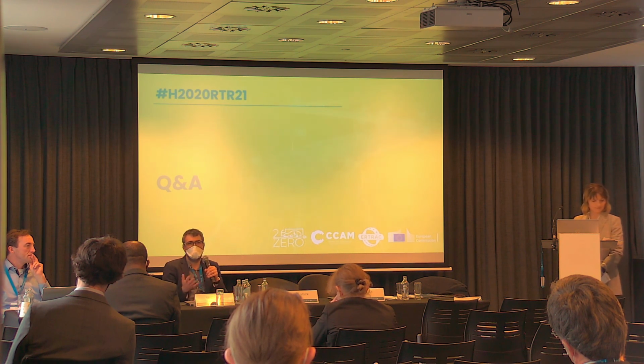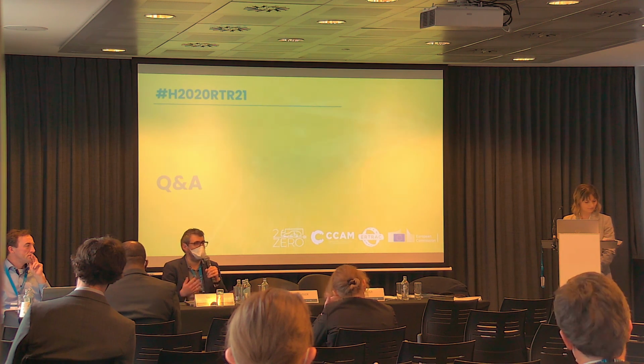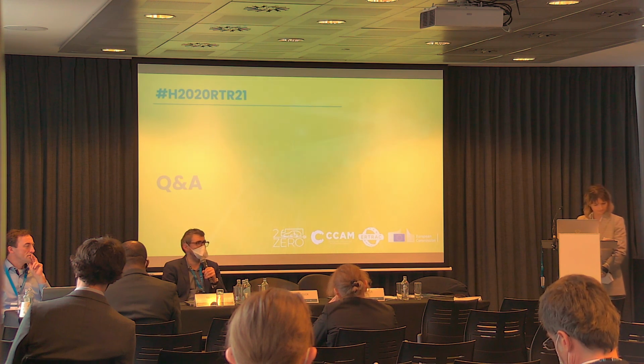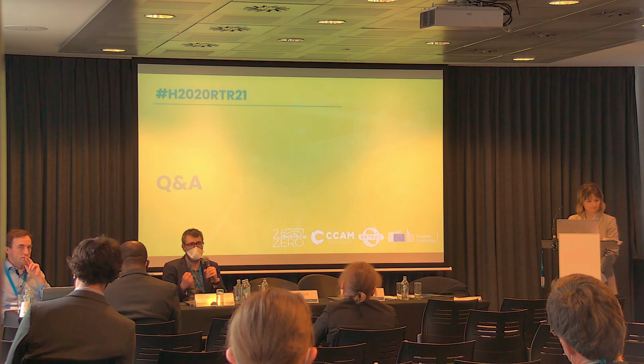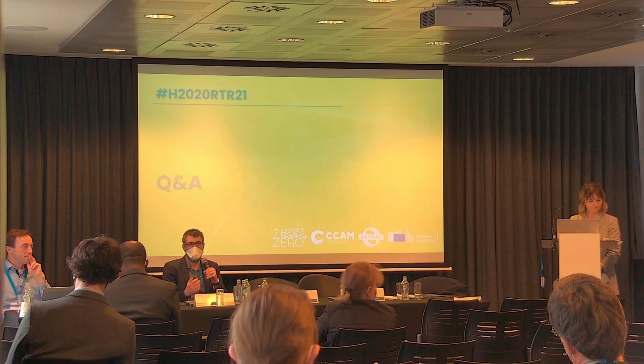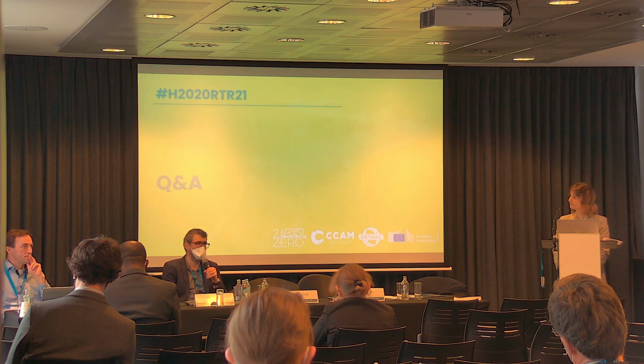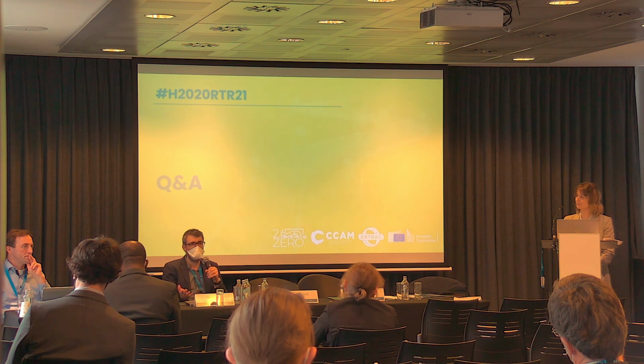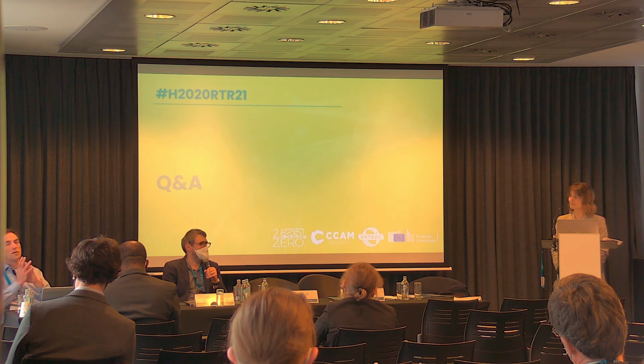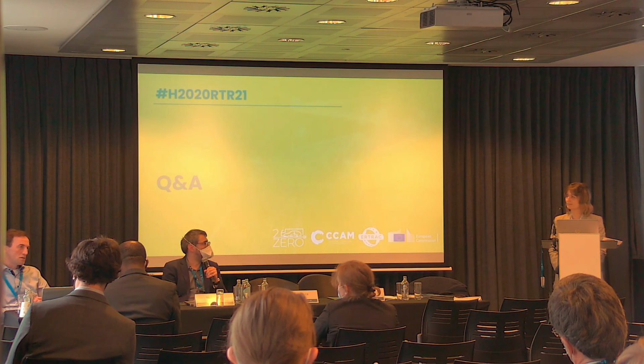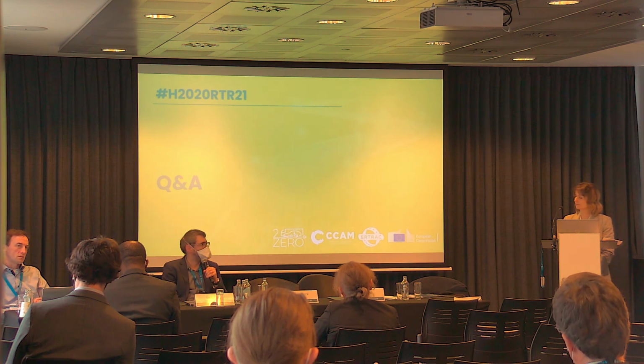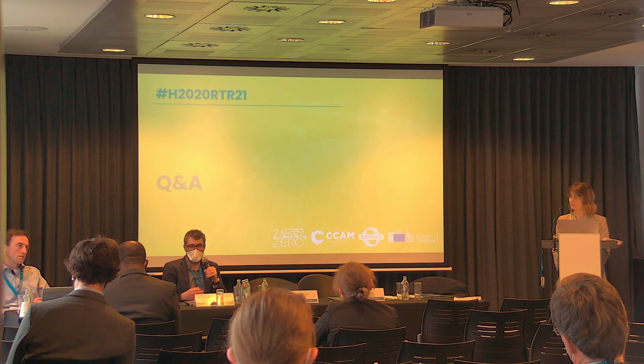Also, we discovered that some simulation techniques were not fit for the new materials that we are using. FEM modeling for silicon-based anodes was not very fit because of the high deformation that we had. The deformation was too high and not represented correctly by this system. So we needed to switch to other descriptions like DEM and so on, with other limitations. We still have a lot of things to learn, but with the amount of computational power that we have now, it's easier and easier.